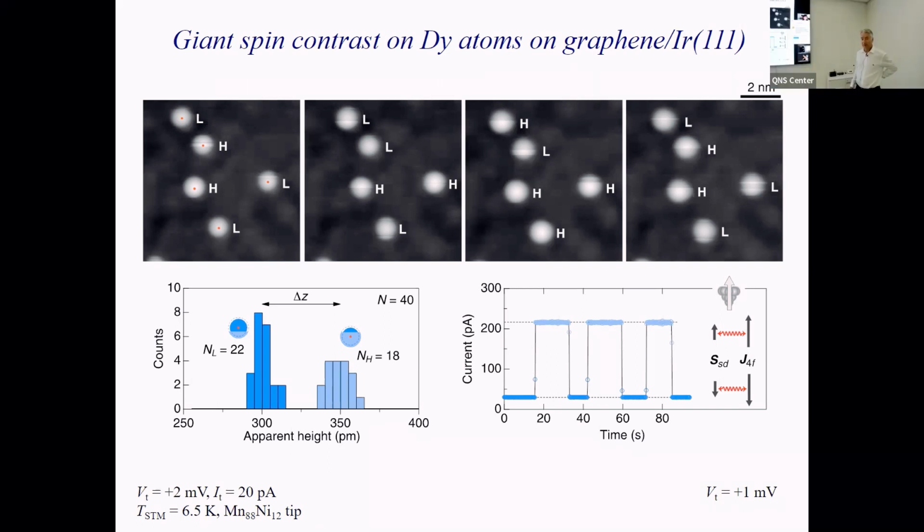So in principle, the magnetic stability comes from the 4f electrons, not from the outer electrons. And the 4f has this high magnetocrystalline anisotropy, and the outer electrons are just coupled by 100 millieV or so to the 4f electrons, so the outer ones follow. Does this reply to your question?